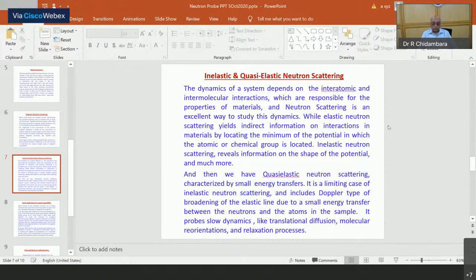I would like to add that in a recent paper from Japan this year, they have studied the dynamic behavior of hydration water in phospholipid membranes. Very difficult to study this. And they used various techniques, and they found that quasi-elastic neutron scattering is the most effective method for this purpose, because you can study the dynamics of both the water molecules and the lipid molecules. And of course, they used selective deuteration.